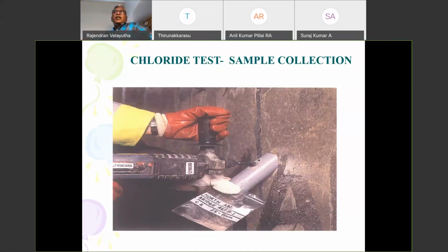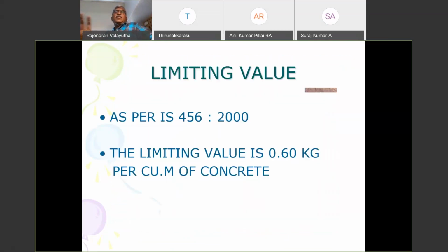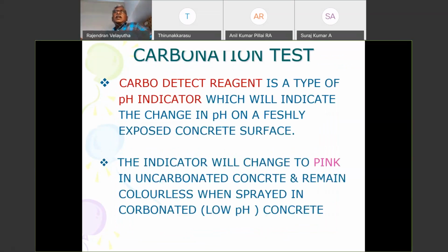When you test at the laboratory, it will give 0.59, and then we go happily, yes, it is within the threshold limit of 0.6 kg per cubic meter as per IS 456. So that should not be done. So we need to go to different levels. If the structure is going to be very, very important, then you can go even to increments of 10 millimeters, 0 to 10, 10 to 20, and so on.